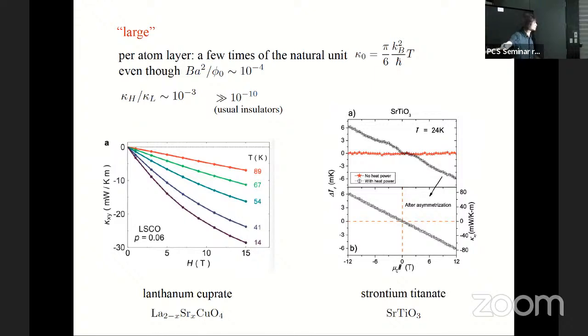The magnon in LCO has a gap of 50 Kelvin. First of all, that, and moreover, the magnon has some discontinuous features when you change the magnetic field. The magnon band has some transition, but when you tune the magnetic field, you don't see anything strange here, right? So both of those reasons make us think it may be unrelated to magnon. And next, there will be one more reason to think that this is a phonon contribution, from further experiments, right?